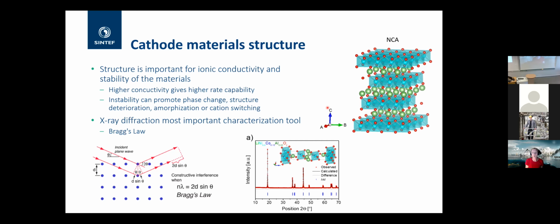Here, X-ray diffraction is only used for crystalline structures, crystalline materials. If you have an amorphous material, you're not going to be able to see anything, because it depends on an X-ray wave coming in and diffracting from the structure as shown in here. The data that you get out looks something like this, where you have a diffractogram showing clear diffraction lines, and the diffraction lines indicate then the